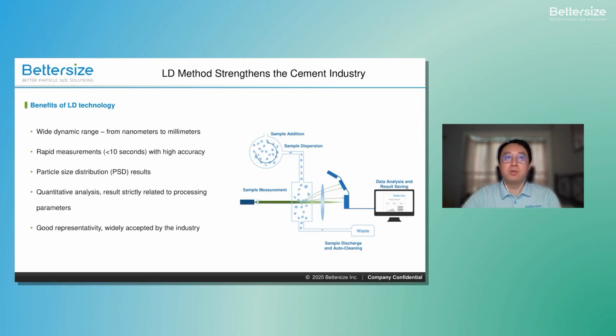Meanwhile, the LD test efficiency is good. Usually, 10 seconds would be enough for a single testing process. That makes it possible to monitor particle size changes and have some valuable time for taking action. Also, the results come with good quality. A large amount of particles can be measured with a single test, thus ensuring a good representativeness of results.